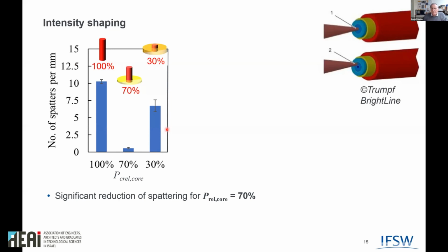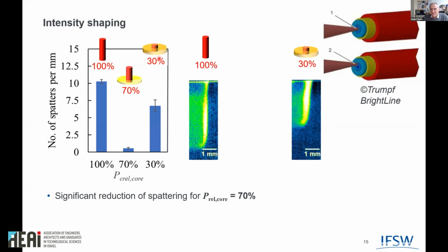And if you now look at the number of spatters for these three intensity distributions, you see that we have very much spatter where 100% is in the inner part. Here at 70, when you have a little bit around the hot spot, it dramatically drops, and then it comes up again if you have the large spot. And it's not very surprising, given these images I was showing before. So this is the capillary which was created when everything is in the inner core. This was the capillary which was created at the higher speed when everything was in the outer core. And in between, you remember, here we had fast and small spatters, here we had large and big spatters.